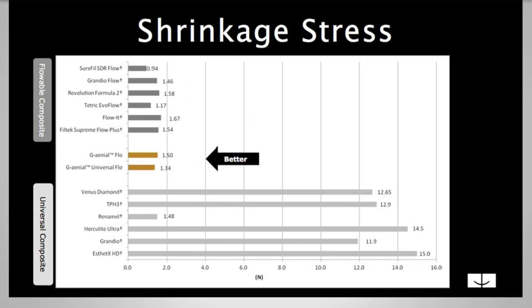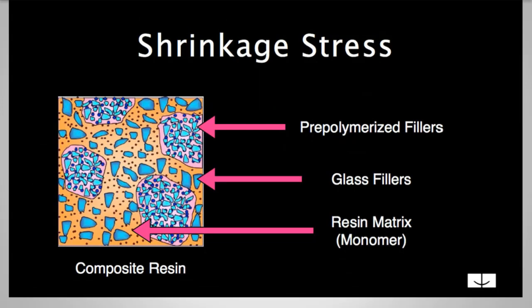So where does shrinkage stress come from? Shrinkage stress in our composite resin can come from a couple of different places. The most prominent is in the resin matrix or in the monomer. And so there are different ways or different monomers that we can come up with to reduce shrinkage stress. Also, the amount of filler, how heavily filled by weight is the composite. That oftentimes can also reduce shrinkage stress. How many glass fillers and their size can also play a part.